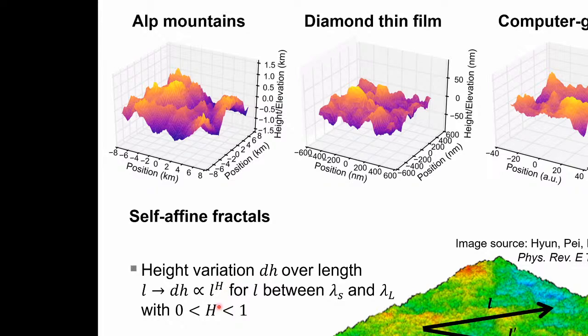This seems to indicate that these distances grow unbounded, but let me illustrate that this is still a flat surface. So if we ask the question, what is the mean height over this distance L? So if I do delta h over L, then I get scaling that looks like this, L to the power of minus 1 minus H, and this is a positive number, this 1 minus H, so this actually goes to 0 as I look over larger and larger distances. So these are nominally flat surfaces.